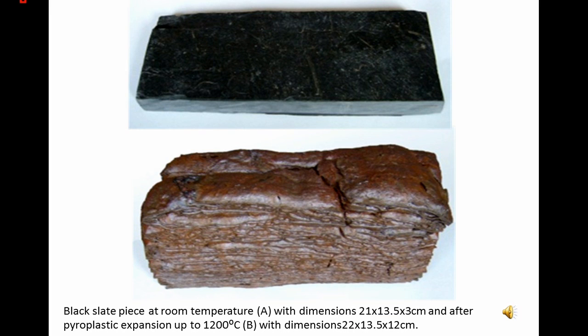Submitted to a heating process similar to the ordinary ceramic process, black slate can expand 4 times its volume and becomes a distinct material in terms of mineral and chemical composition, structure, and appearance. Black slate thermal expansion is the result of gaseous formation and of the vitrification process of its mass during the thermal treatment that results in the formation of a glass that provides gas retention.